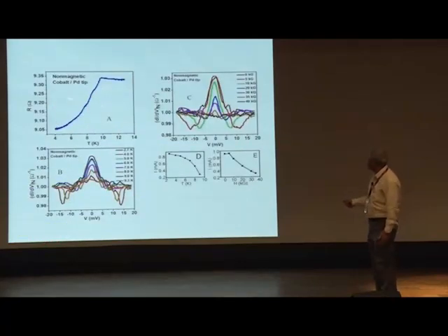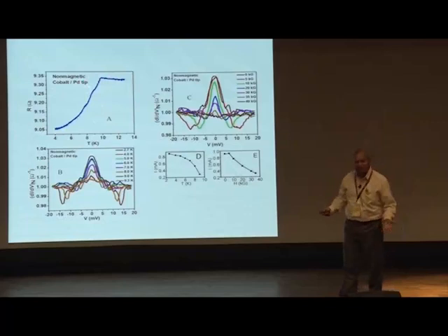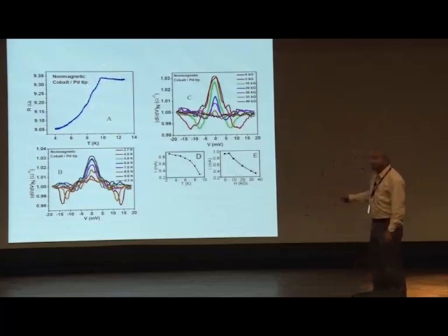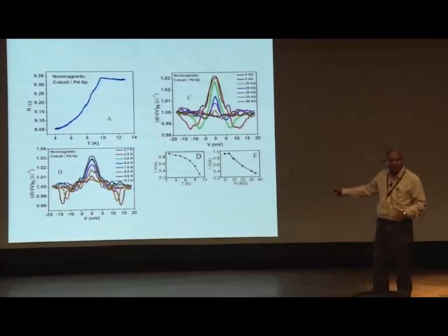Now we take data with another tip, palladium, which is also a normal metal, just to confirm it. Again we see the superconducting transition, and we see these features in conductance versus voltage as a function of field, and with temperature variation. Additionally, compared to the other one that I showed, we have two symmetric dips around this peak.